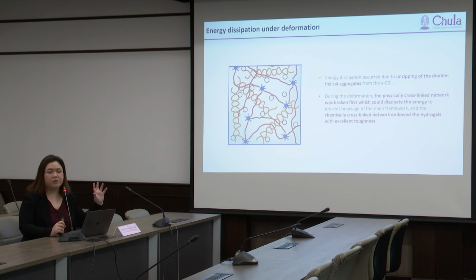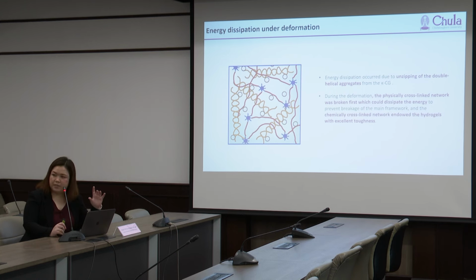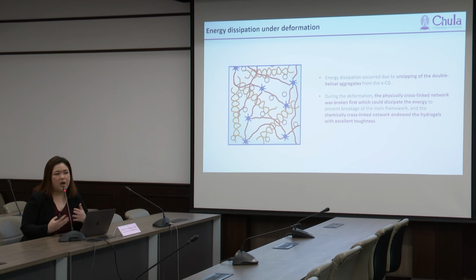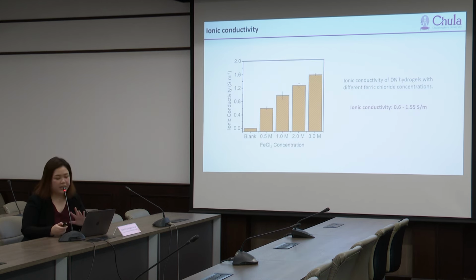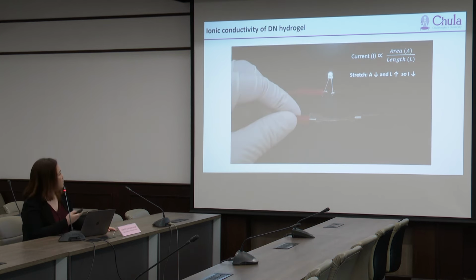So we would like to use this hydrogel as a conductive sensor. At first, we need to make sure that our hydrogel has enough ionic conductivity. So we also vary the concentration of the iron chloride solution. And then you can see that when we increase the concentration of the iron chloride, the ionic conductivity increased up to 1.5 Siemens per meter.